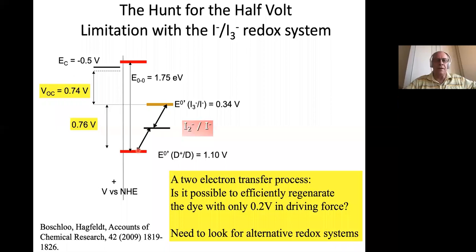So that's where Jeanette and I thought that, okay, here is where we need to attack it. And the problem with iodide, triiodide, is that it's not a simple redox system. It goes through intermediates, and we identify this iodide-iodine radical as an intermediate species, which also has a redox potential. So when we bring back the electron to the oxidized dye from the intermediate, we have maybe 0.3, 0.4 volt. And that's the driving force to regenerate the dye. Then we lose 0.3 volt to make the I3 minus.